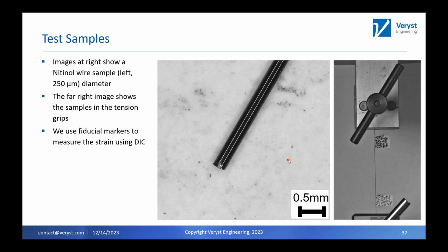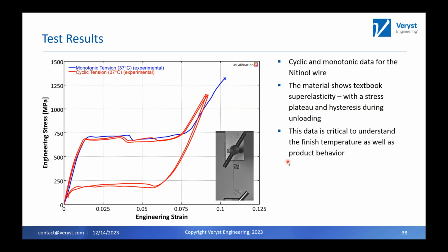The first question you might come up with is, can you go to failure? And the answer is not really. We test to failure. Failure typically happens at the grips, so it's going to be a conservative estimate of the failure. If you could give us lots of material, we could use a method with capstan grips, but generally our clients are only able to get 10 or 15 millimeters of this, and we need something like 300, 500 millimeters, probably even more than that, something on the order of a meter to do one of these tests in actuality with the capstan grips. And then you could get failure a lot better.